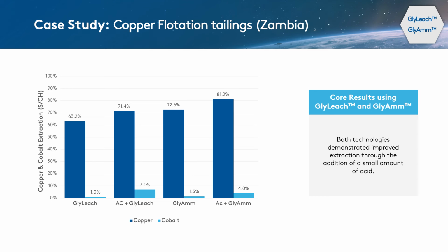The third example is related to copper flotation tailing in Zambia. We used two of our technologies for this specific sample, both GlyLeach and GlyAmm. For both technologies, we are able to improve the extraction using a small amount of acid. As you can see in this graph, the y-axis shows copper and cobalt extraction, and the x-axis shows the different technologies that we have used. For example, GlyLeach would be able to extract 63% of the copper and 1% of the cobalt. If we do the acid curing before the test, we could extract even more copper, around 71% copper and 7% cobalt. For the GlyAmm system, again, it's the same.